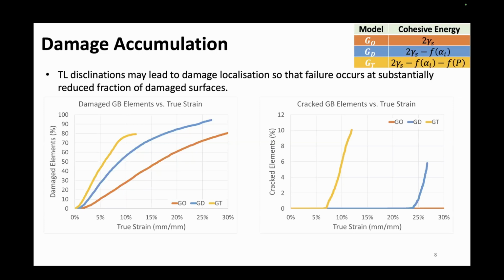And when we turn our attention to this one, this is the percentage of cracked elements in the overall assembly. We can see the GT starts at around 8% true strain and quickly fails at around 12% strain. For the GD model, which considers disorientation, it didn't start until 24% strain, and it also failed quite quickly, but not as quickly as the GT. And the GO model, which is the baseline model, didn't fail until very high strain.